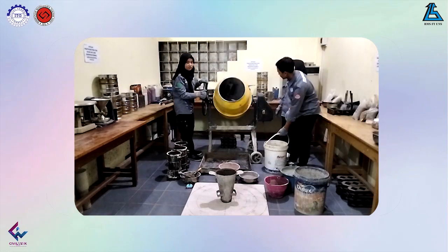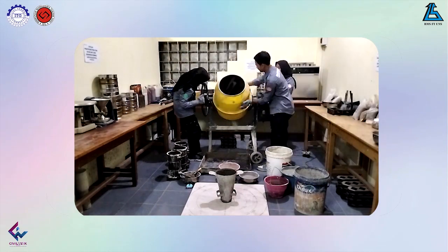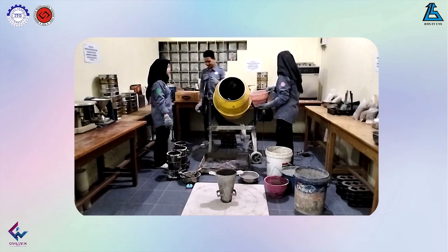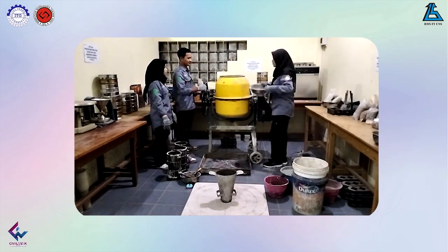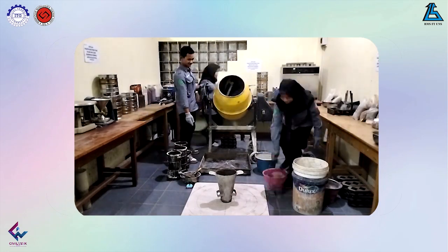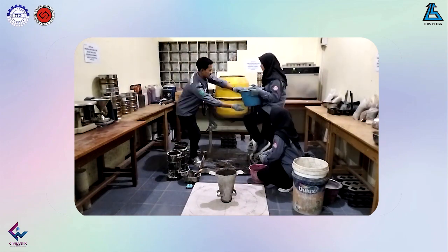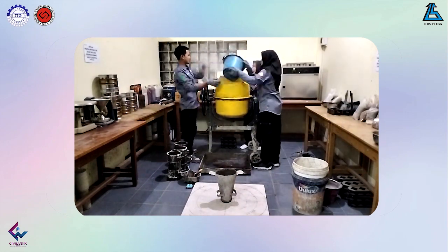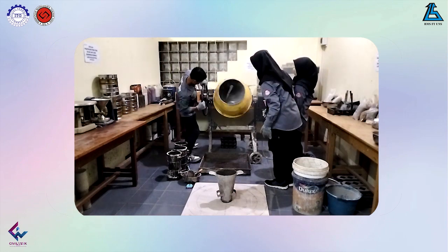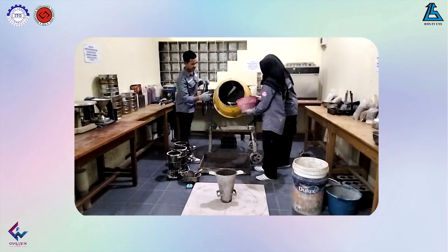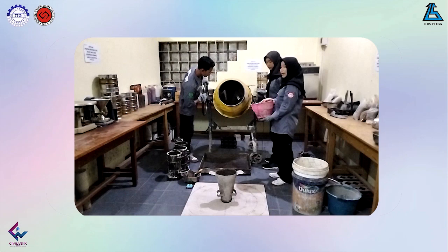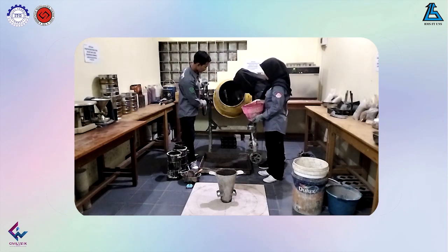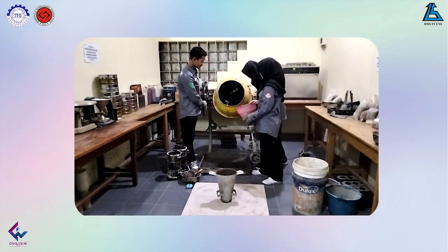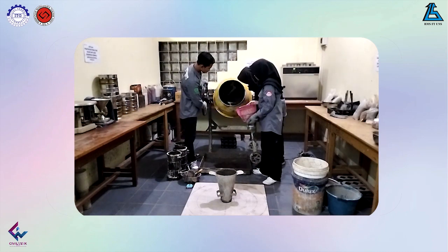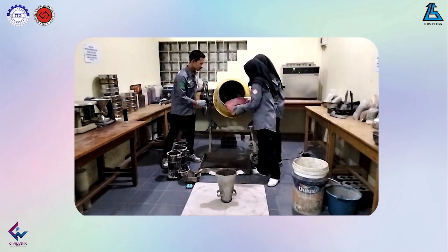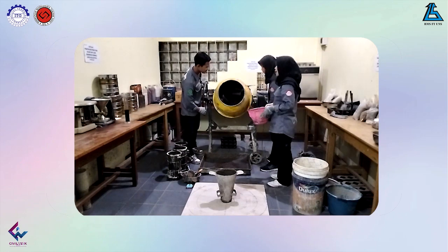First of all, turn on the concrete mixer. Enter the coarse aggregate as much as 12.6 kg for 3 samples. We use crushed stone from the Cimanuk River. The stone was previously dredged, then broken down and adjusted in size, that is, it passed the 12.5 mm sieve and was retained in the 2.36 mm sieve. Next, add 9.9 kg of fine aggregate,